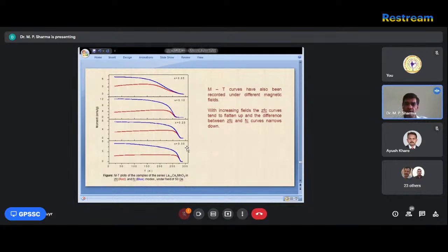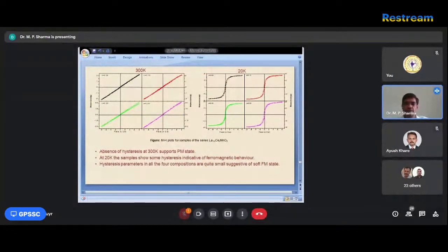So now this is the MH curve at room temperature, and another at 20 Kelvin for the 4 samples. There is an absence of hysteresis at room temperature, which indicates a paramagnetic state. At 20 Kelvin, the samples show some hysteresis, indicative of ferromagnetic behavior. The hysteresis parameters in all 4 compositions are quite small. These are suggestive of a soft FM state, meaning on the basis of this you can say the material is a soft magnet.